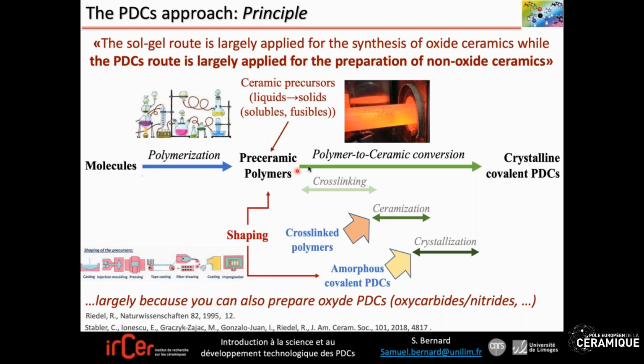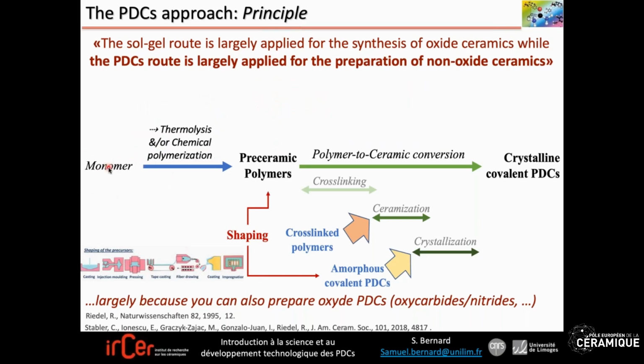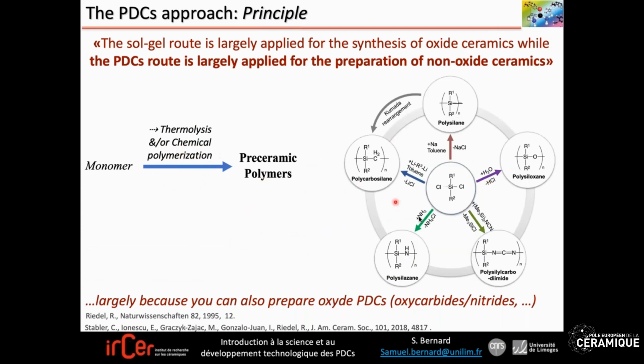So the precursors are the pre-ceramic polymers. They can be prepared as liquids, gels, solids, soluble, fusible, or insoluble or infusible. The starting materials, the molecules, can be a monomer, which is thermolyzed, heat treated at, I would say, between 50 degrees C and 400 degrees C to form your pre-ceramic polymers. It can also react with a low molecular weight compound, what we call chemical polymerization, as generally seen with organosilicon precursors. Dichlorosilanes are considered as monomers, so they react with a low molecular weight compound, as you can see, ammonia, to form pre-ceramic polymers, polysilazane, for example, as a precursor of silicon nitride. But you can form a large range of polymers, polycarbosilane, for example, a precursor of silicon carbide.